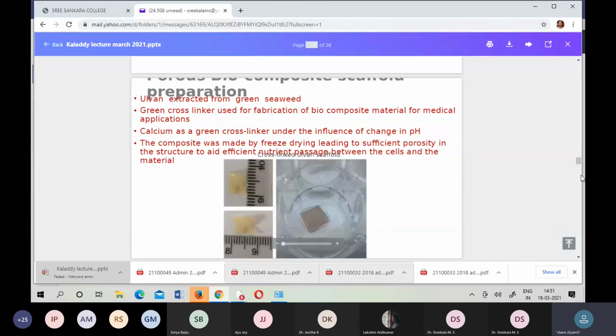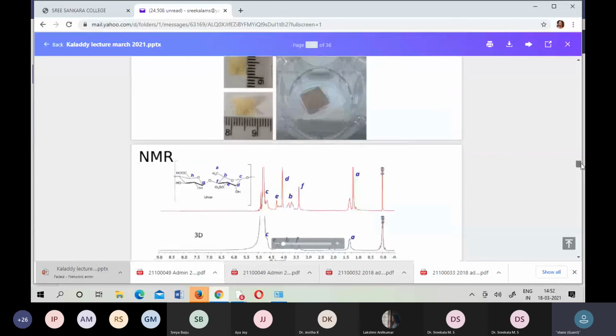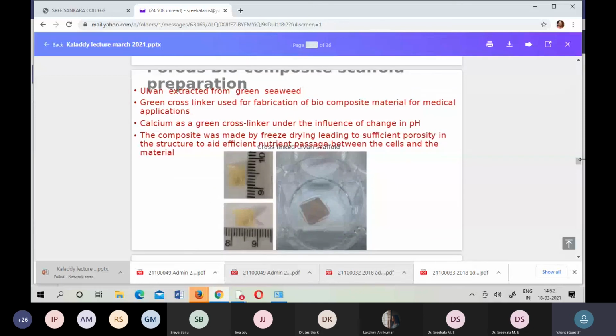So in the picture, what we are showing is like a normal film. Similarly, we are able to get the 3-dimensional scaffold of the same polymer Ulvan, and we did the cross-linking. The NMR structure clearly shows the first one is the normal Ulvan material, whereas the second one is the 3-dimensional scaffold. In the scaffold, the cross-linking happened with the presence of calcium chloride. The calcium is doing the cross-linking process, so obviously some peaks are disappearing, some peak intensities are increasing. That is indirectly proving that cross-linking happened.